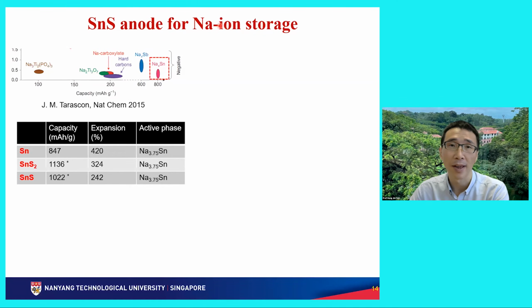So now I want to focus on the anode one, tin. So tin material is alloy type. Even in lithium batteries, people explore the tin-based alloy type materials to replace the graphite. So for example, this diagram shows the anode side for sodium batteries. If we look at the sodium tin alloy, the capacity can be 800. That means if you want to have a capacity match with the cathode side, you don't have to give too much weight. You can use much less material.